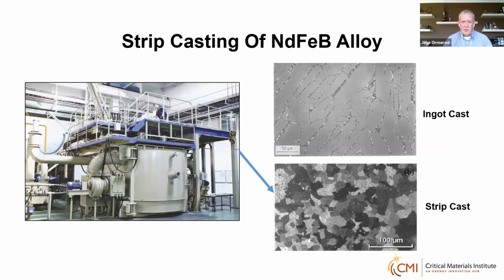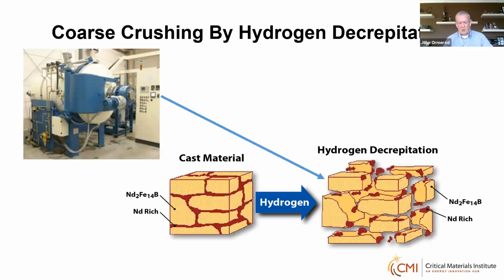So what was discovered by quenching from the melt at a much faster rate, as I said earlier, 10 to the 4 degrees per second, is that you could suppress the formation of alpha iron and produce a very equiaxed structure of the 2-14-1 surrounded by a very fine-grained neodymium-rich phase, which is essential for the development of good sintered magnetic properties. Hydrogen decrepitation.